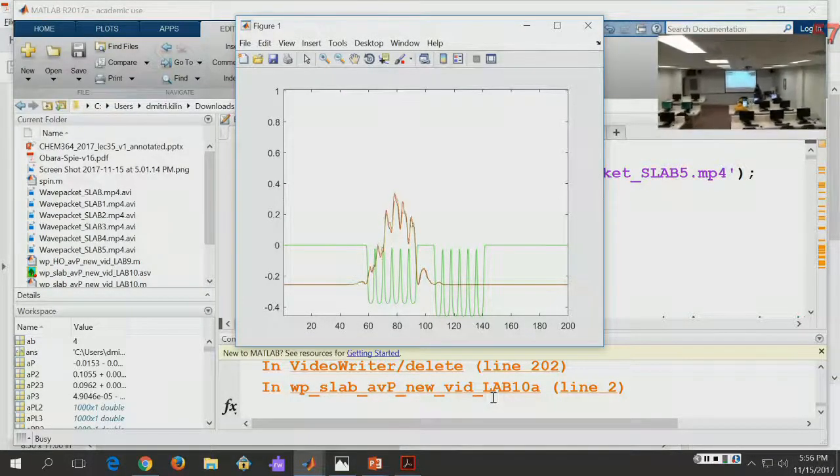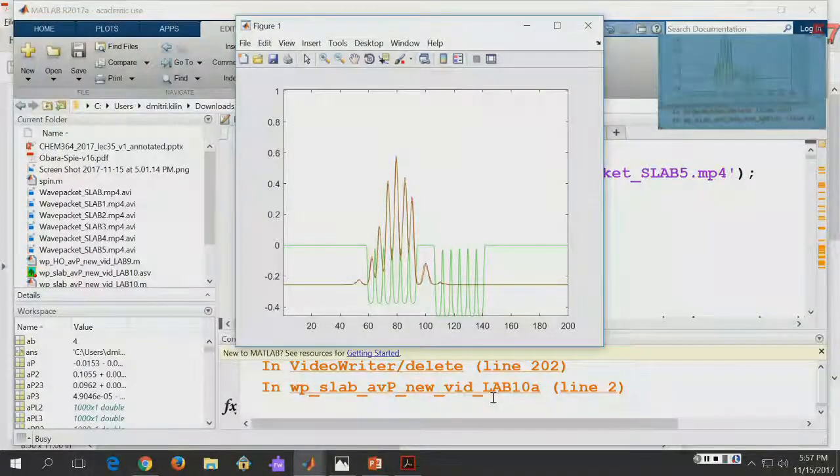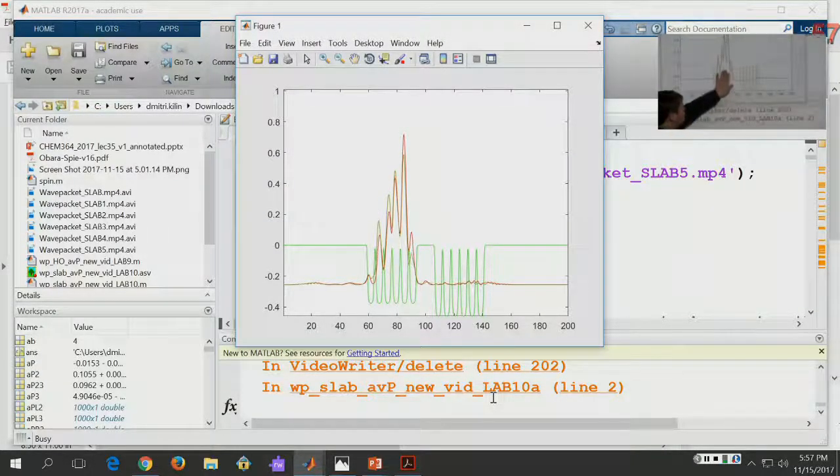So what we are modeling right now, we create the initial density only on one side. So this absence of a couple of atoms models the physisorption rather than chemisorption. So there is a little insulating tunneling regime. And now the transfer does depend on the excitation of the initial electron, not only spatial localization, but overall energy, the distance between these layers, temperature, and as we will model in, well, not in a couple, but in like 20 minutes, the presence of voltage. That was choice number 1 by Mark.